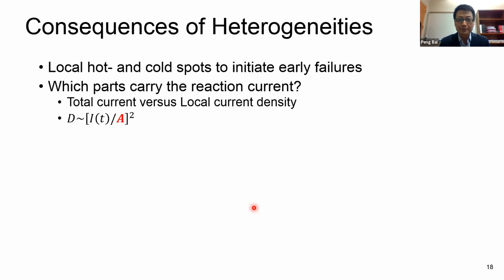But more fundamentally, the question is, which parts carry the reaction current? When you design your battery, should you use the total current or the local current density? The answer is obvious. We should use the local current, the working current density. And this is more fundamental for electrochemical characterization, because always the most important parameter we need to identify is the diffusion coefficient of lithium in the solid material. It has a square law dependence. It depends on the current density squared, and current density is of course the total current divided by area. If you have an error in your area, you will magnify the discrepancies here, right?